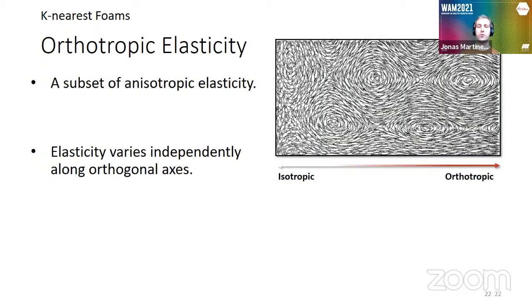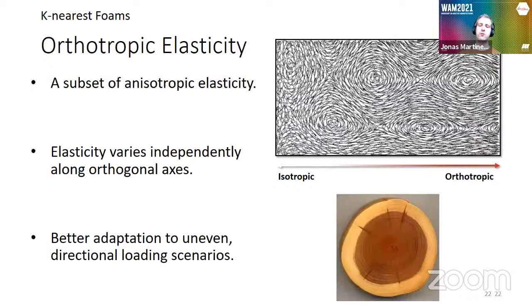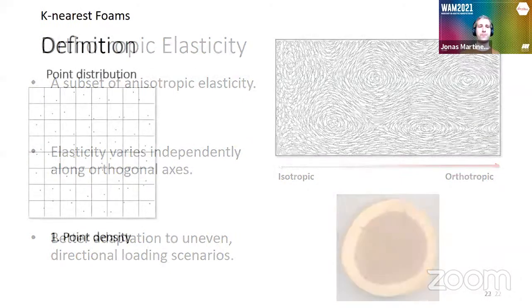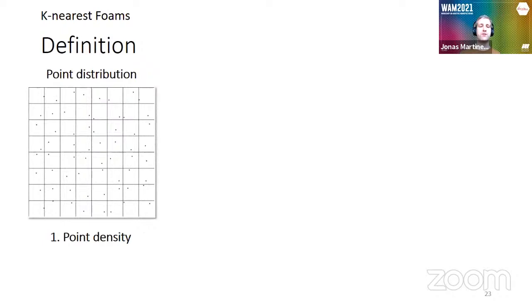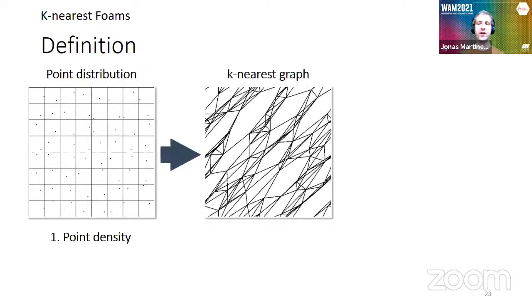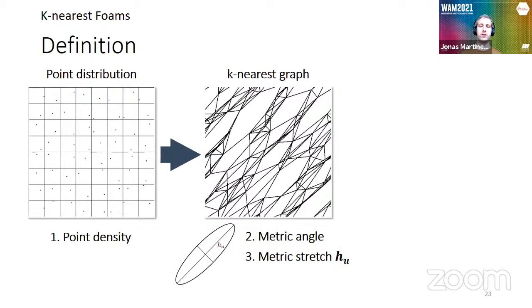So here is what we obtained with our approach. I'm not going to enter into details. But basically, we were seeking some material, such as wood, that has better adaptation to uneven loading scenarios. So algorithmically speaking, we also have control of the point density procedurally. And what we consider is the k-nearest graph of this set of points. A k-nearest graph is basically, imagine that for each point, you connect it to the k nearest ones, and you connect them under some specific metric. So not the Euclidean one, but a stretched metric, basically. It is the Euclidean one plus some affine deformation. And we can control the angle of this metric and also the stretching factor.